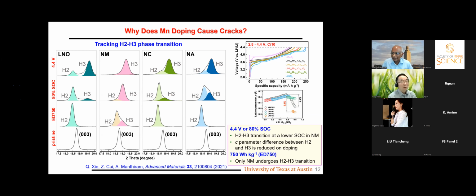Sorry, there is one question in the chat room. How can you determine the chemical state of nickel vacancies in the lithium nickel oxide? Nickel vacancies where? The chemical state of nickel vacancy. No, maybe nickel ion, not vacancy, right? Vacancies won't have any chemical state. So nickel valence. I mean, once you know in the beginning how much lithium you have extracted, you know what the oxidation state will be. Otherwise, if you want to use some equipment, you can obviously use XPS, but that will not be accurate. Any technique we use will not be very accurate. There will be some error. But once you know the capacity, at least in the beginning, we will know based on the lithium content what the nickel oxidation state is.